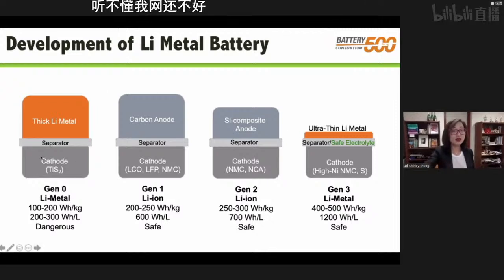Right? So in the 1970s, when Professor Whittingham built the first lithium metal batteries, the cathode had no lithium in it. It's titanium disulfide. So for this reason, he needed to put a very thick block of lithium metal on the negative electrode side. Our situation is completely different. We have high lithium containing lithium cobalt oxide, lithium iron phosphate, or lithium nickel manganese cobalt oxide.